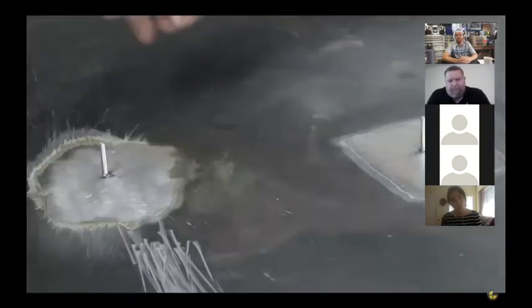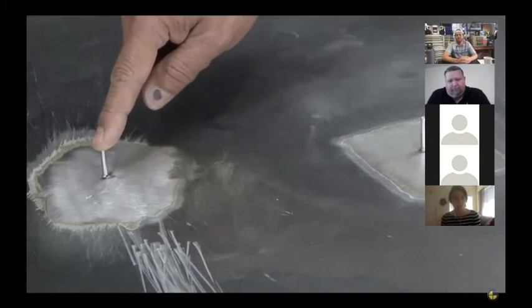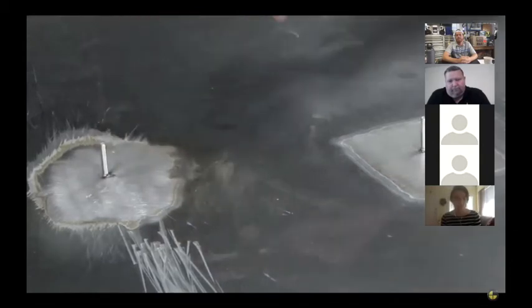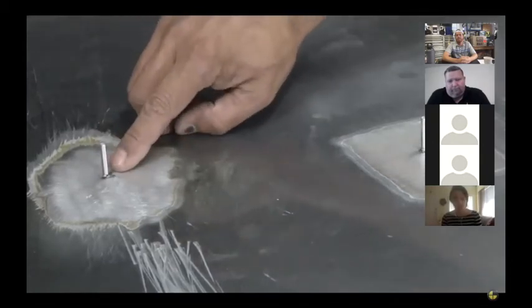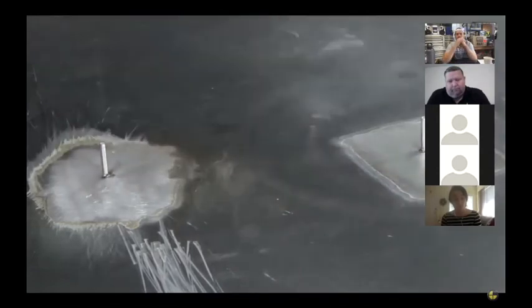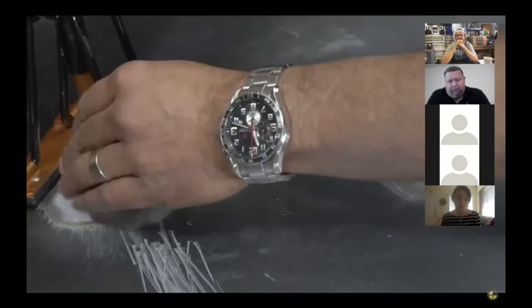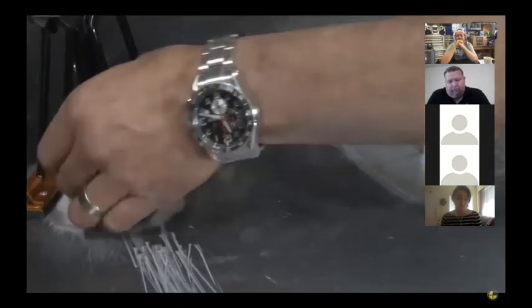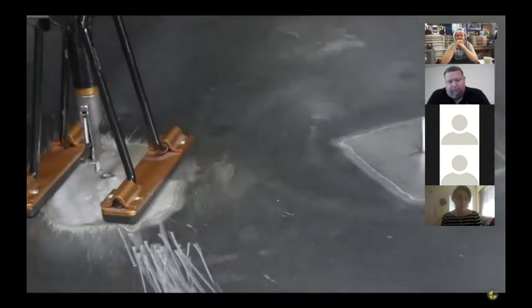So we're looking at a stud that was burnt into an area that wasn't prepped properly. It had a big spark and a big flare up. You can see the burn flash on the edge and the burn around the edge of it, which shows that it was burning contaminants. And when we try to pull on it, it pops right off.